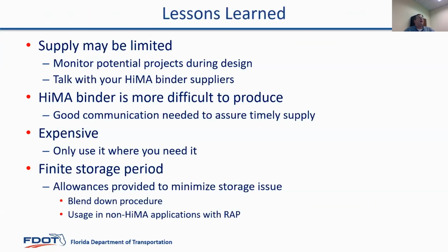Well, to wrap it up, I want to talk about some lessons learned, especially if you're just starting to use high polymer binder. Supply may be limited. If your suppliers aren't used to supplying it, and you start putting it on multiple projects, you may have a supply issue. So you're going to want to monitor the potential projects during design. You don't want to overspec it until your binder supply has a chance to catch up. And I speak with experience on that, because we experienced that issue as we ramped up once we put it in the standard specs. So you want to monitor that, be careful.